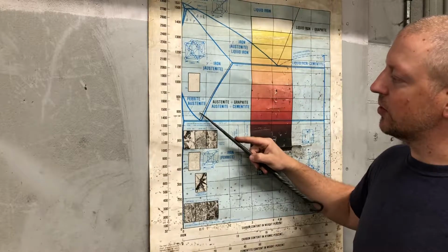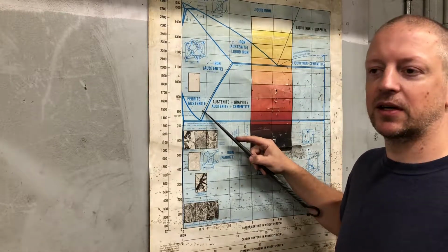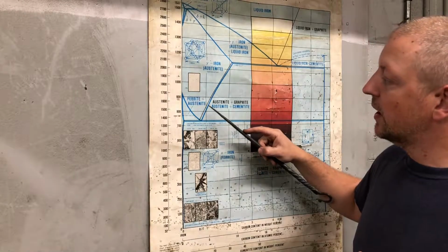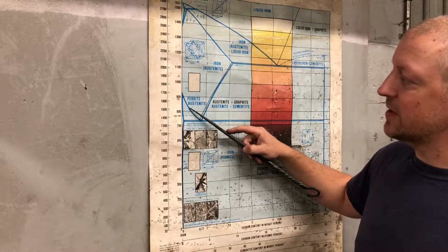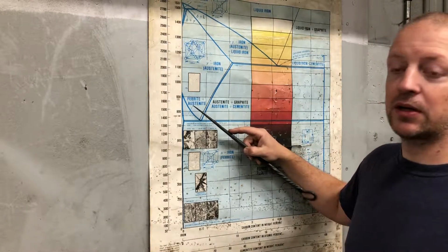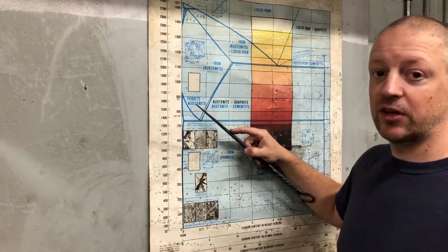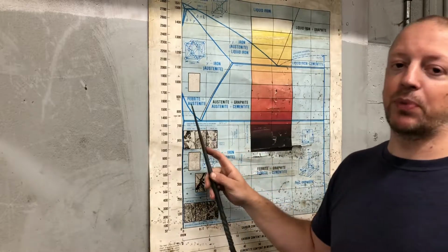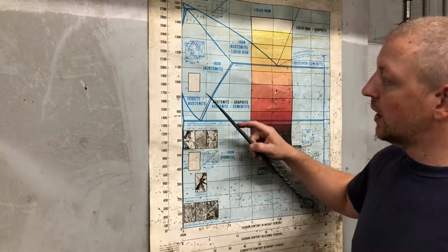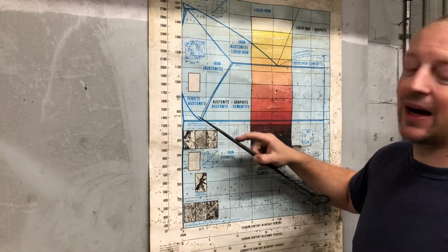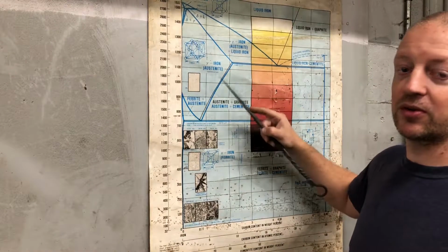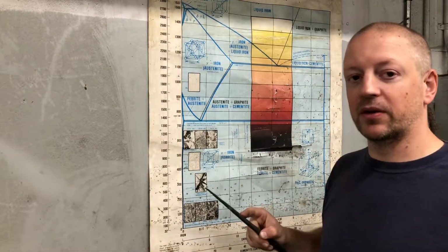And at that temperature range, you're not getting rapid grain growth, so it works out great. But for something like 1050, or for that matter 4140 or 5160, these hypo-eutectoid steels, so less than eutectoid, you really have to go hotter to get full austenite in order to then quench and get full martensite.